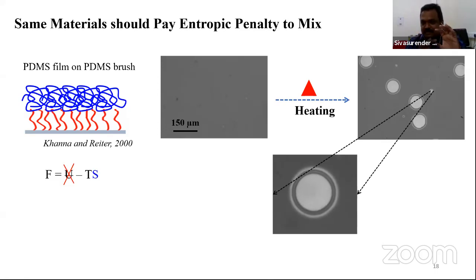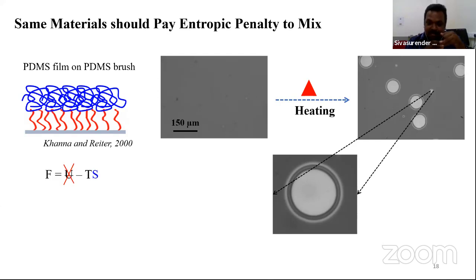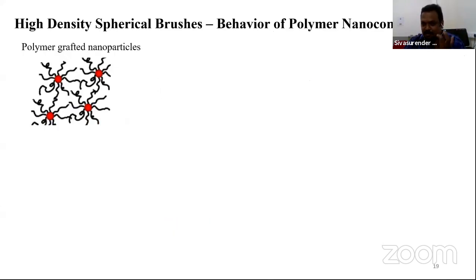This nucleation is essentially a thermodynamic process, so there are no external forces needed. You just go to the optimum temperature where you could see these holes growing. And now, materials of the same nature, PDMS on PDMS, but the PDMS which you have put on top is running away from the PDMS at the bottom, right? That running away is what you're seeing here. This retraction of fluid of exactly the same chemical nature was quite surprising. And now we know the reason, which is entropy, right?